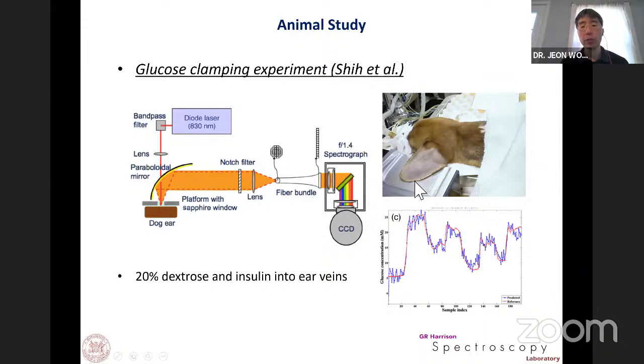Around that time, we were working with Bayer Healthcare. And since we could measure the glucose concentration from the whole blood, the next step was applying the technique to the animal experiment. So we performed a glucose clamping experiment. The beagle dog was sleeping, and we connected 2 lines to the animal. One is dextrose, and the other was insulin. By controlling the flow rate of insulin and dextrose, we could modulate the blood glucose levels of the animal as we want.